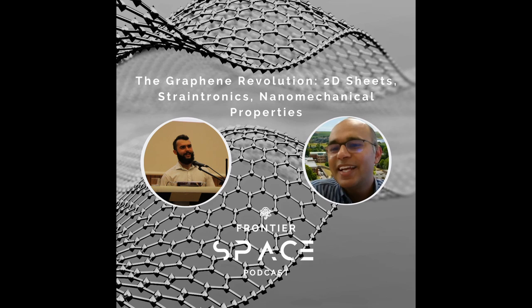When I say efficiently, I mean with less potential bias, and you can reach nearly 300 degrees centigrade. And I don't think someone has recorded such a high temperature. People have done something with graphene oxide and other materials, but they hardly go beyond 100, or maybe some people have done carbon up to 200, but 300 no one has reported yet. Just pure carbon, no doping, nothing.